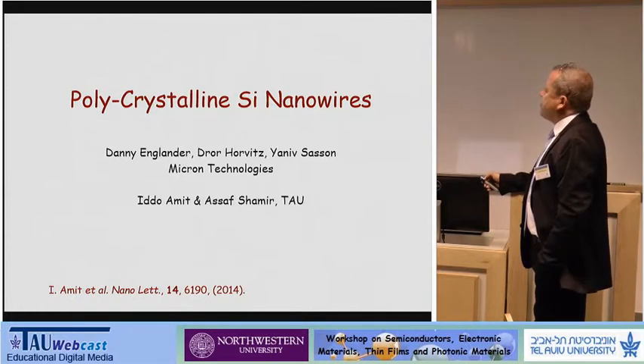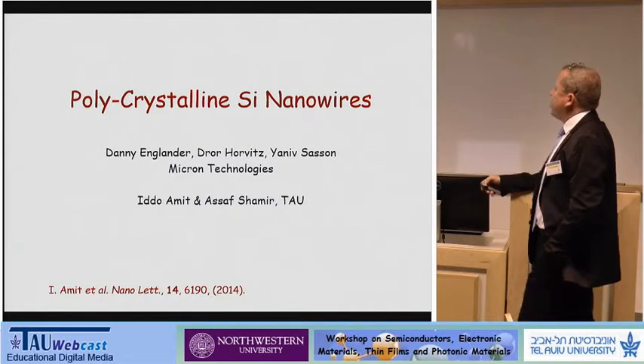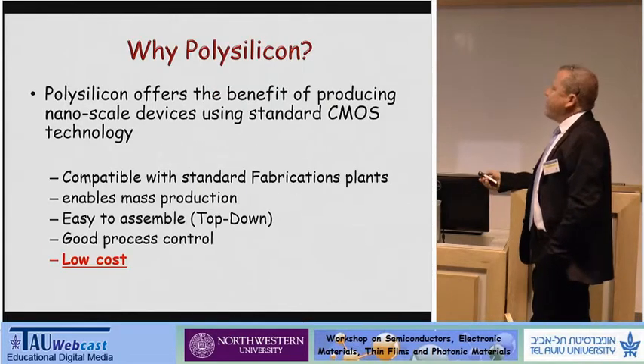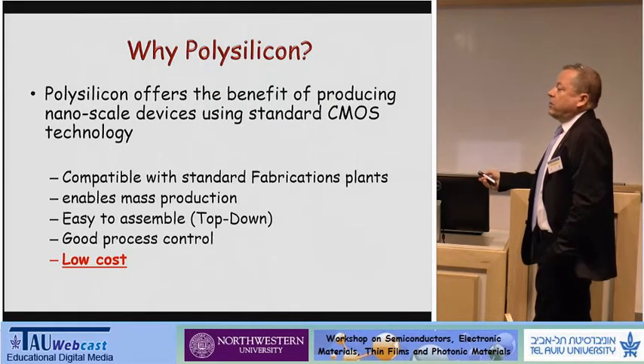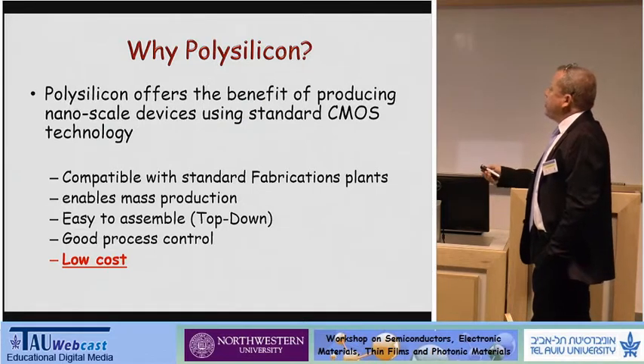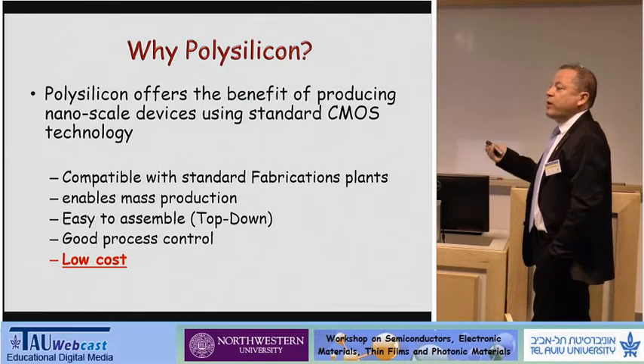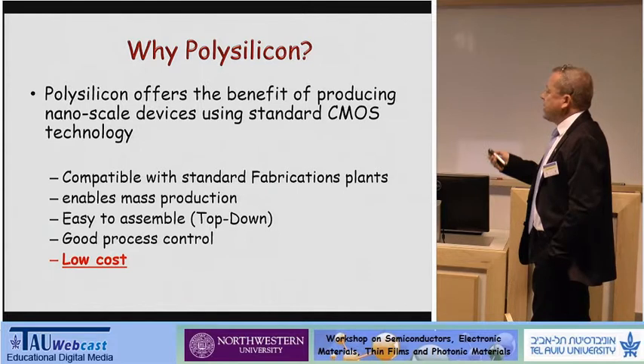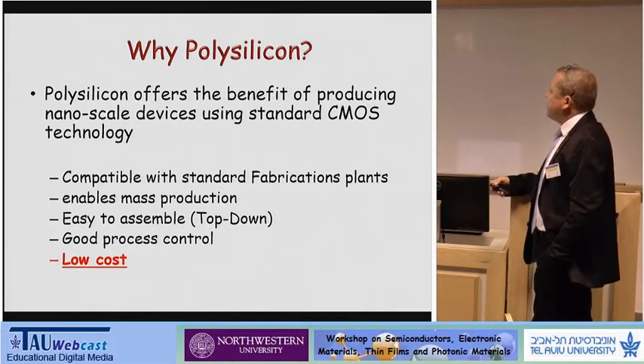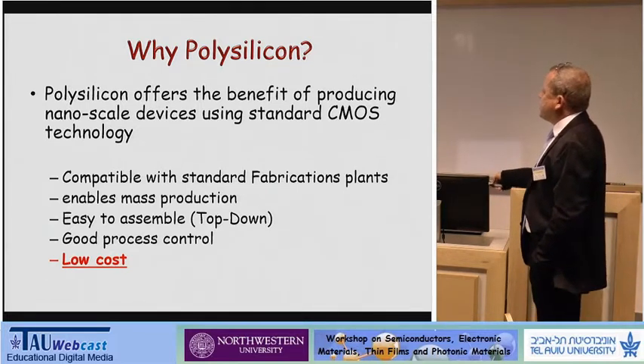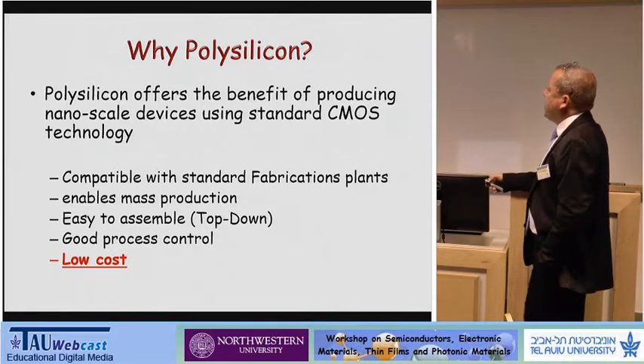In this study, we measured polycrystalline top-down grown nanowires. Why polysilicon? Polysilicon is cheap, but the big problem, as you will see now, is that it has grain boundaries. And the grain boundaries, in some cases, have a large disadvantage. But the message is that this is a low-cost technique and can be done very easily in a fab.